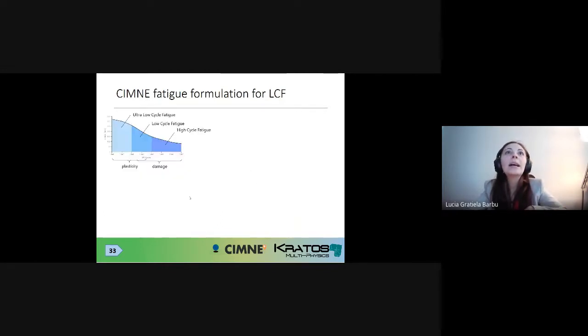Okay, now low cycle fatigue. Low cycle fatigue, this gray area between the plasticity and the damage domains. There is a big question that you have to answer when you're speaking about this area. And this is, if you're using a plastic damage model, which you should be using for low cycle fatigue, how much energy should you devote to plasticity and how much energy should you devote to damage?